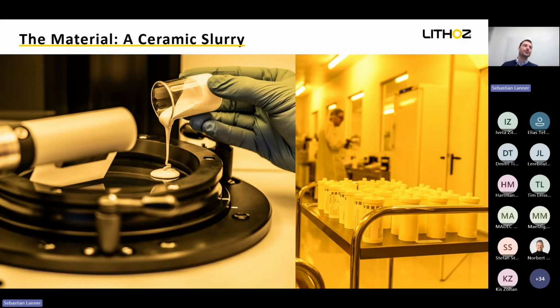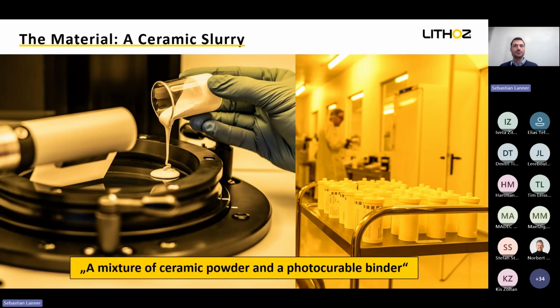So in this slide, I want to give you a short introduction to the printing material, because the material we print with and the material of the final part is quite different. Our printing material is a mixture of ceramic powder in a nanoscale and a photocurable binder. You can compare it very similar to a resin from various SLA printing technologies. This combined creates a highly viscous slurry. This viscosity you can compare with honey or a Greek yogurt. Our machine has several technical features to deal with this viscosity. And this is one of the reasons why we do not provide the material for non-machine customers, as the risk for failure would be significant. So this is about the slurry.